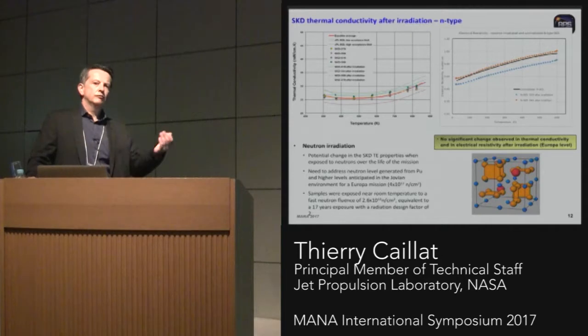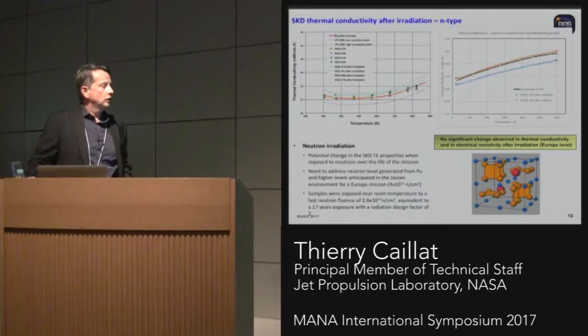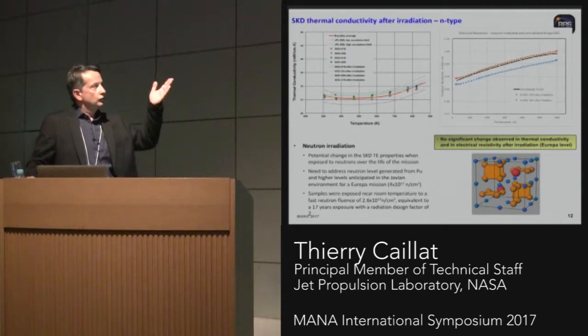So typically when we develop those new materials, we do a neutron irradiation test to see what would happen, and you can do this by defining the level. That particular test was done to account for the self-radiation over a 17-year mission, as well as reaching Europa, so being exposed for a shorter period of time in the Europa environment. You calculate the neutron flux, then do the irradiation in the reactor and measure the properties before and after, to see if any defects have been created that change the transport properties. The most sensitive property would be the thermal conductivity, and we typically do this at room temperature, so there's no potential self-healing of a defect.